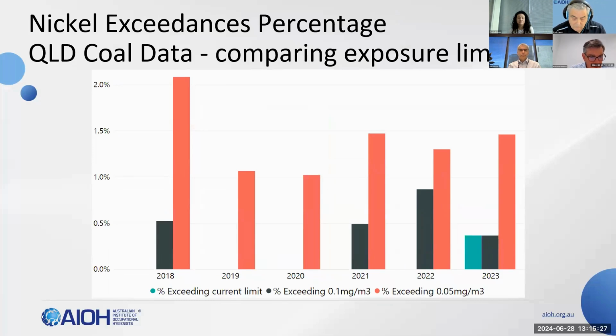So applying the exposure limit of 1 milligram per cubic metre, which should be in green, it's about 1% of the samples exceeding. And then again, if we go to 0.1, it's about the same. And looking at the rule of thumb, 50% of the OEL, it sneaks up to about 1.5%. So this is nothing like the exceedance rates that we see for manganese.